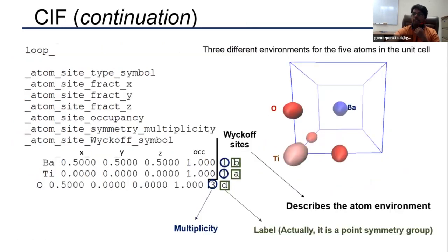And the most important information that you can find in a CIF file is the location of the atoms in the unit cell, more concretely, the atoms in the basis. Here in the slide, I show you the atoms of barium titanium oxide in the cubic perovskite structure. The basis contains 5 atoms, but in the CIF, you can see that there are only 3 atoms: one for the barium, one for the titanium, and only one of the 3 oxygen atoms. This is because the 3 oxygen atoms share the same neighborhood of atoms. Basically, they see the same neighborhood of atoms.